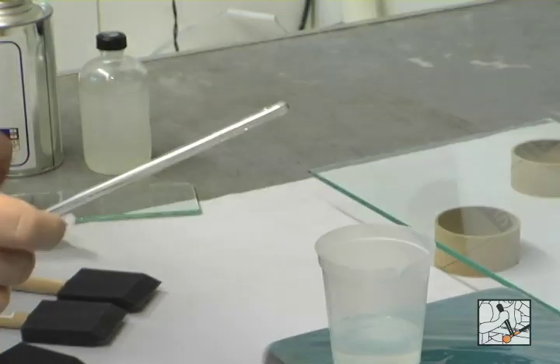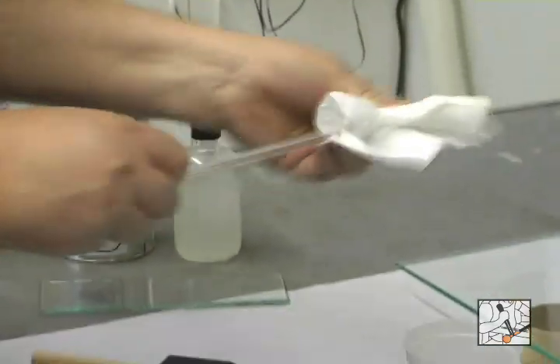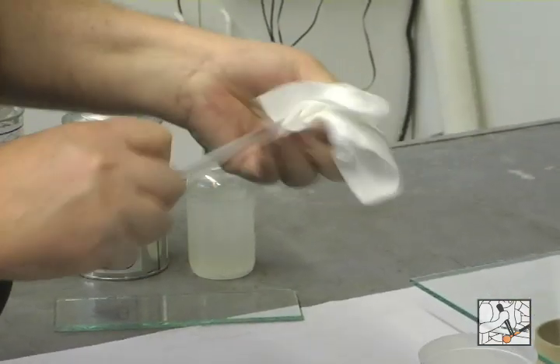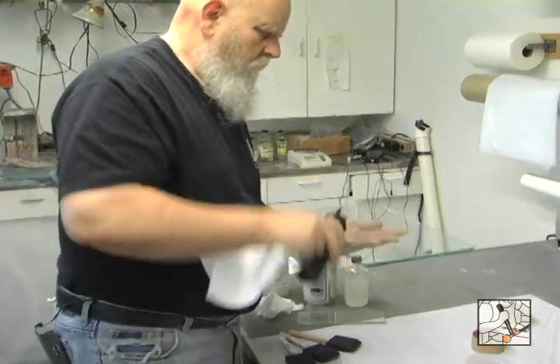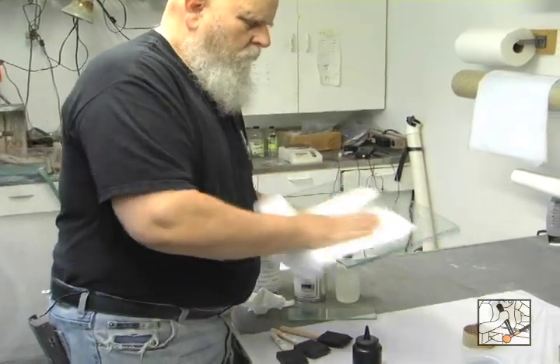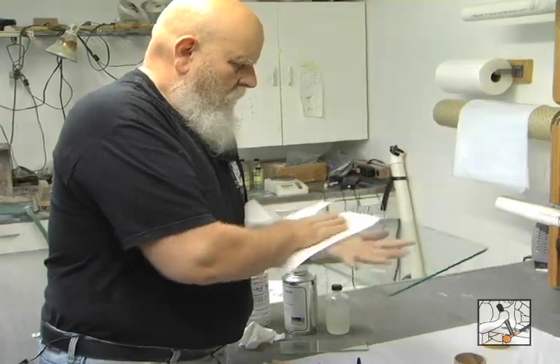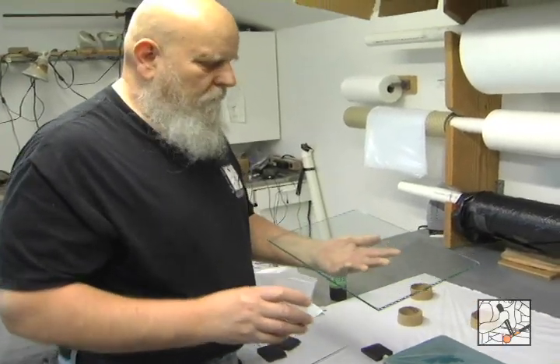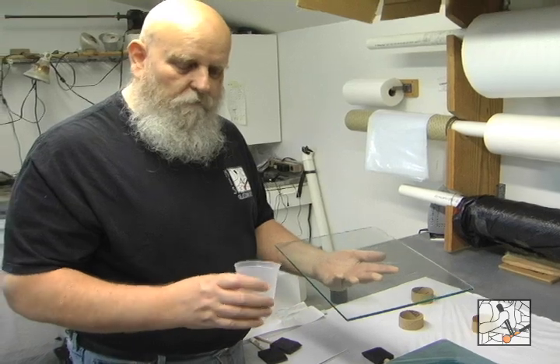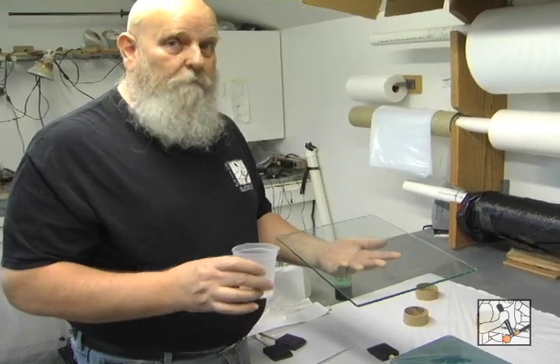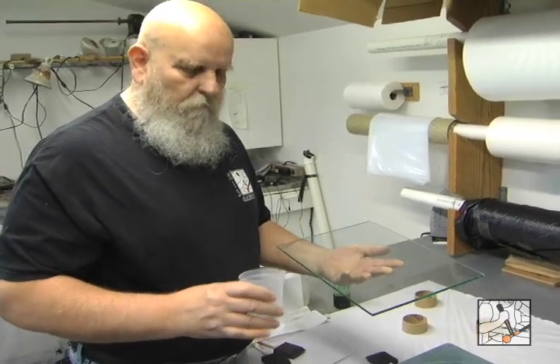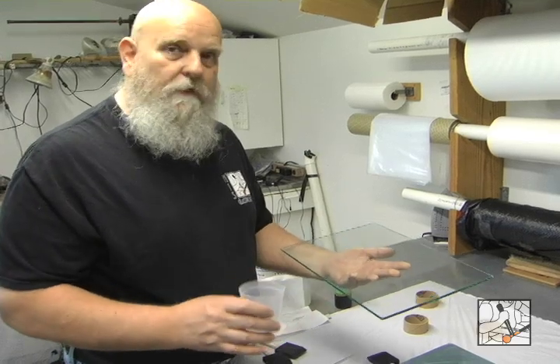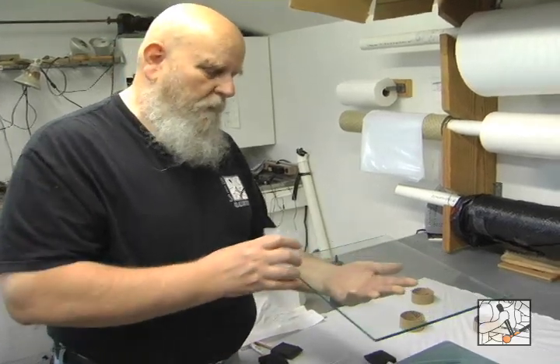Time to clean my stirring rod. One final cleaning with a little bit of acetone. FlexTech has approximately 15 minutes, plus or minus a little, from the time you begin mixing. If I've already mixed it and it sat for a couple of minutes, I've got about 10 minutes now to smooth it on.